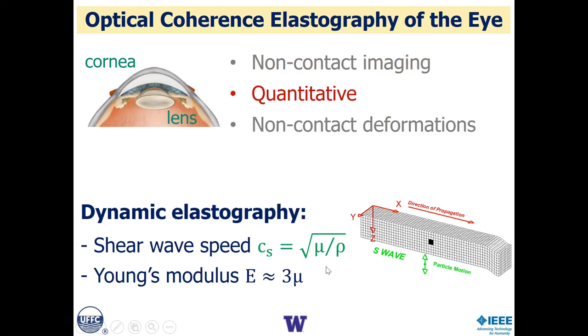And the idea is you will launch a mechanical wave and track propagation of that mechanical wave with your real-time imaging system. In the simplest case, if you can launch a bulk shear wave into the soft tissue and then use the imaging system to track that, then locally you can estimate the wave speed of that wave. The wave speed is simply proportional to the square root of the shear modulus. That's just material density, which is pretty constant in soft tissue. So that modulus, the shear modulus, is proportional to the wave speed squared.